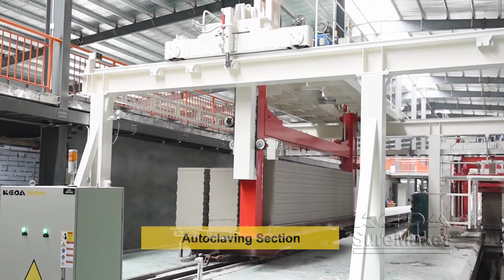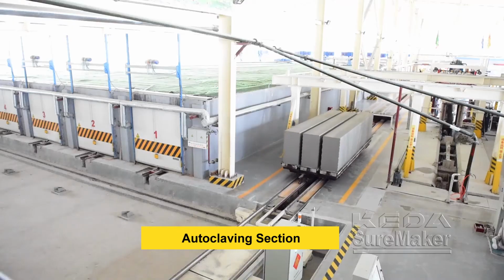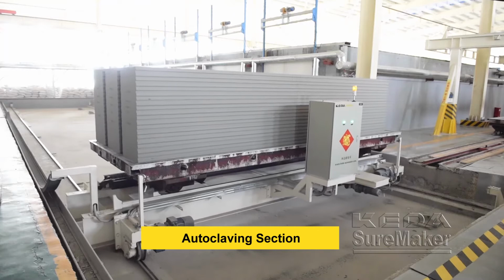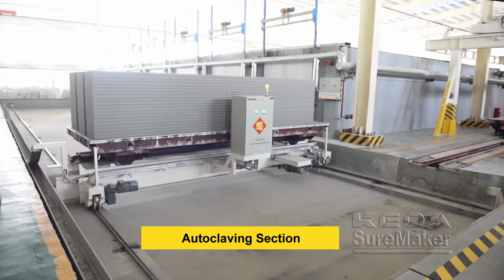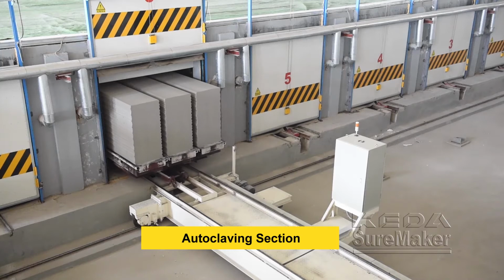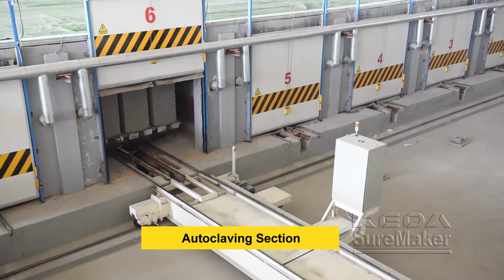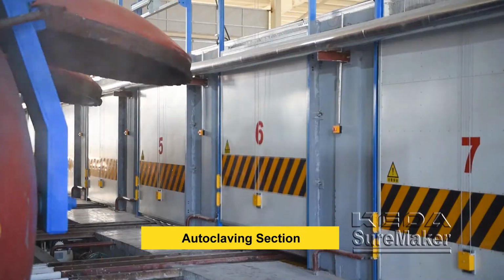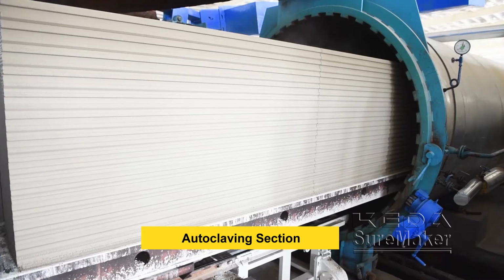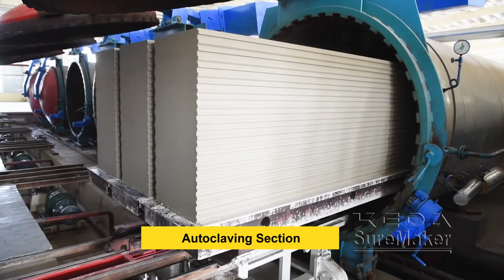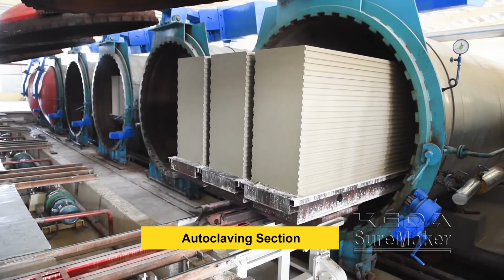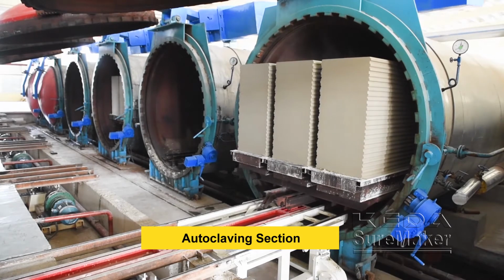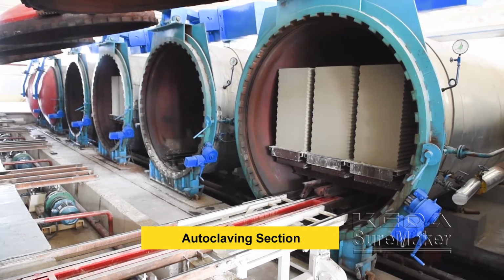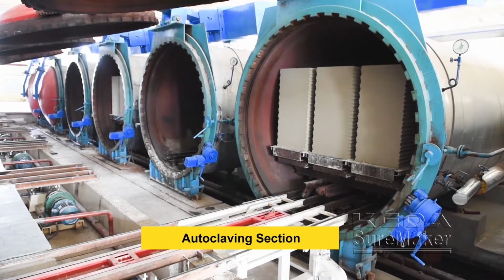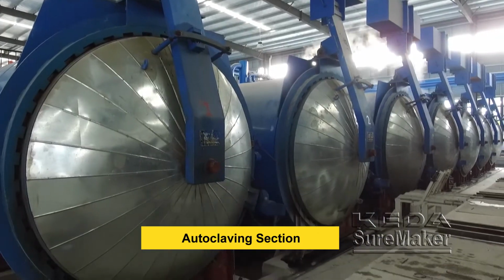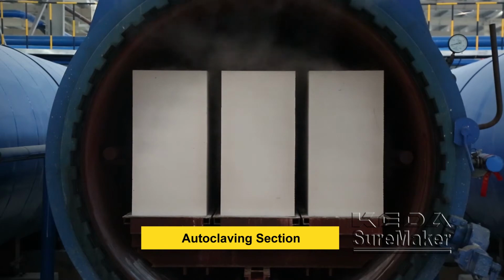The semi-finished product stacking machine transfers the green cakes together with side plates on the three mold curing car. Then, the ferry car will take them for grouping before autoclaving. After grouping, three molds curing cars will be pushed into the autoclave for curing 10 to 12 hours under 200 degrees Celsius, 1.2 megapascal. Steam and autoclave can be reused from each other to save energy consumption.